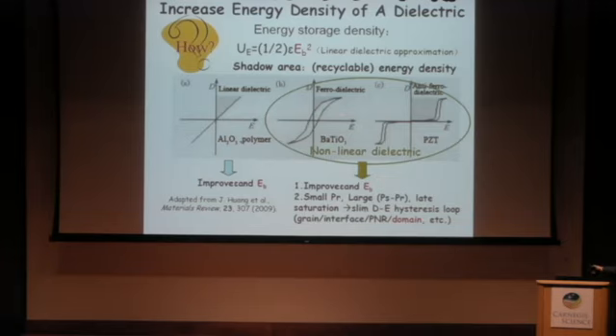At the same time, another key parameter you need to consider in the design is to improve the applicable electric field as large as possible, because the energy that you can store is not only in proportion with the dielectric constant, but in proportion with the square of the largest field that you can apply to this dielectric capacitor. So we can have different ways to design it, like I just mentioned. We need to switch from a square-shaped PV loop into a slim, tilted PE loop. We can design it by grain structure, nano-grain structure. We can design it by interface. By utilizing this interface, we can use relaxers, or we can utilize the domain structure. And this is what I'm going to talk about today.